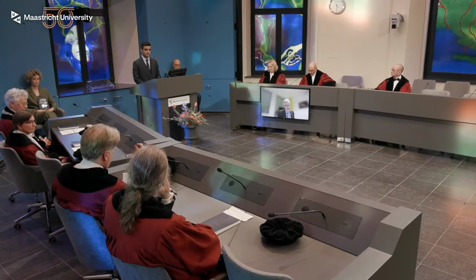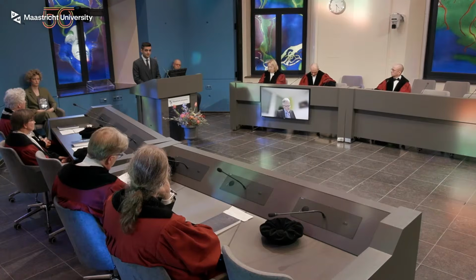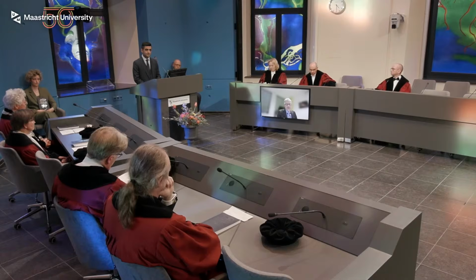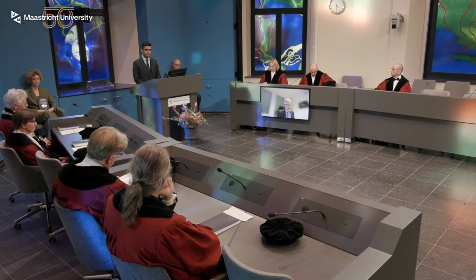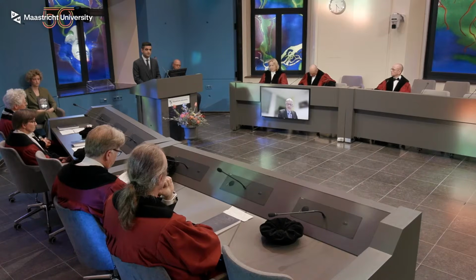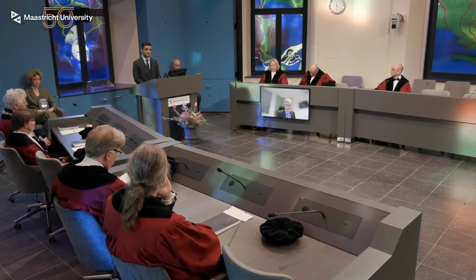Thank you. Yes, the point, of course, with the strain hardening test is that you get a lot of information about the mechanisms happening, but you do not get a lot of information, for example, on crack initiation. And there you have the problem with PP contaminations and maybe also with inorganic contaminations you can have in recycled materials, and maybe then you should also use other methods to have a look at it.